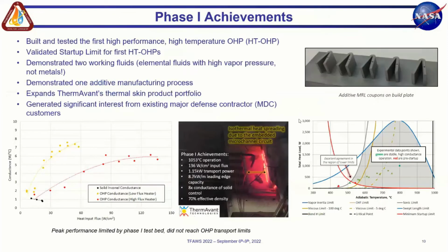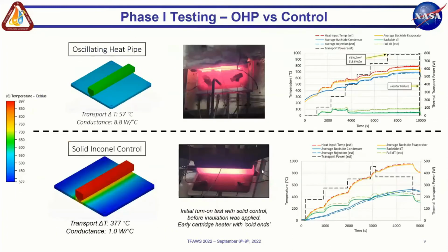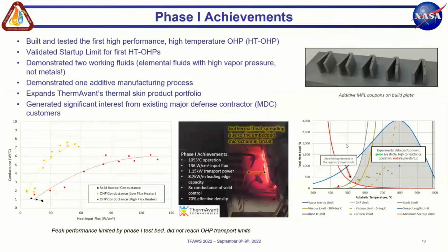All right, so we have a little catch-all summary slide here from phase 1. Built and tested the first high temperature, high performance OHPs, validated the startup limit. This is the onset of nucleate boiling, and in some of the time series plots, you can maybe see it here. You see the DT across the device, the spatial gradient drops sharply when we hit a new power step, and the fluid temperature rises. You see that spatial gradient improve sharply, and we attribute that to the onset of nucleate boiling, which is well predicted by this red curve in the limits chart.